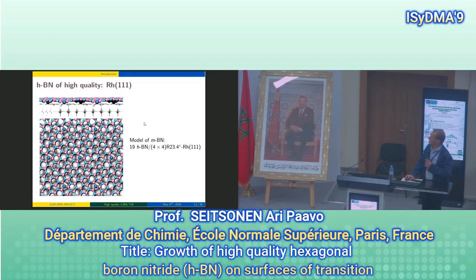And this is then the model Marcello Iannuzzi calculated for the metastable boron nitride. So it is another moiré structure with a different periodicity, and maybe you can see here that some of the nitrogen atoms bind to the top sides of the transition metal, so there's a certain curvature, and this gives rise to the moiré structure also seen in the STM.